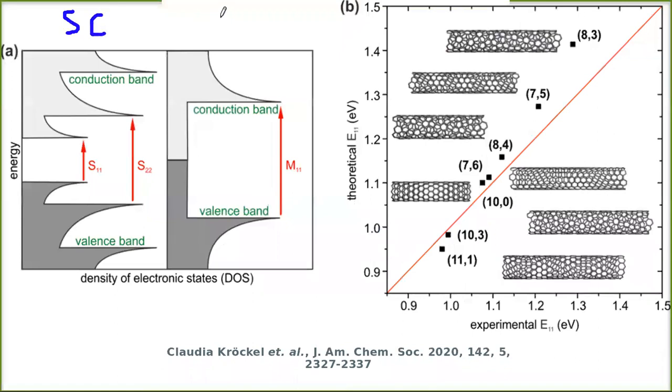We have our semiconducting carbon nanotubes, and we have our metallic carbon nanotubes. In the semiconducting carbon nanotubes, we cross a Van Hove singularity when we have enough electrons to be shared between the alkali metal doping and the carbon nanotube. And then this excess of electrons helps us to cross the first Van Hove singularity, the S11. Then we increase the electron concentration, and then boom, we have a second jump into the second Van Hove singularity, and so on, if we could continue.